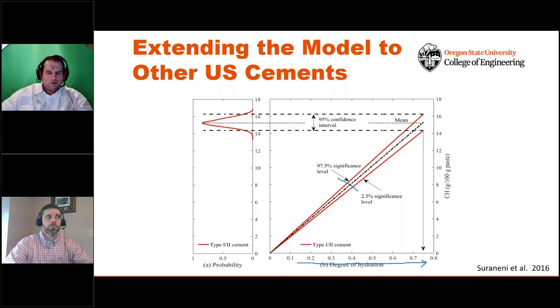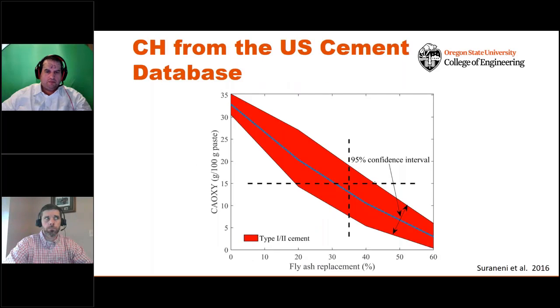So what we can do is we can say for all of the North American cements, this is the type of range of calcium hydroxide that you would expect to be developing in this system. What this really tells us is we shouldn't be comparing a blue bag of cement versus a green bag of cement versus an orange bag, because everybody's producing that to have a very, very similar amount of calcium hydroxide.